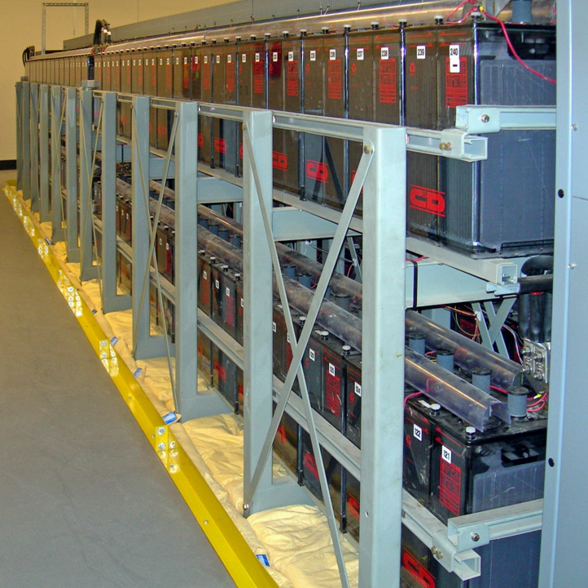For example, in lead-acid batteries, not all the active material is restored to the plates on each charge-discharge cycle. Eventually, enough material is lost that the battery capacity is reduced. In lithium-ion types, especially on deep discharge, some reactive lithium metal can be formed on charging, which is no longer available to participate in the next discharge cycle. Sealed batteries may lose moisture from their liquid electrolyte, especially if overcharged or operated at high temperature. This reduces the cycling life.